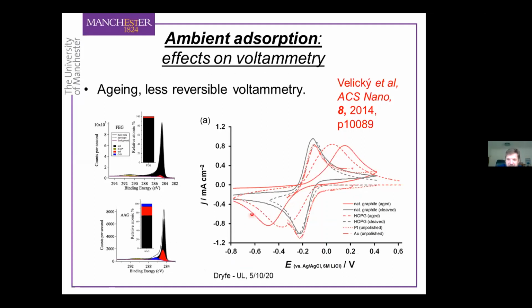And again, it's a similar sort of response to what Pat saw, but instead of looking at repeated cycles of the voltammetry, we're just doing a very simple experiment: the effect of doing CVs with a basic redox couple for a graphite material that's been freshly cleaved, so the basal plane has not been contaminated, or a graphite material that's been aged in the open lab for a while before we do the CV. And you see, if you compare the red CV, the solid red line, with the solid grey line, this one is fairly reversible, and this one is much less reversible.